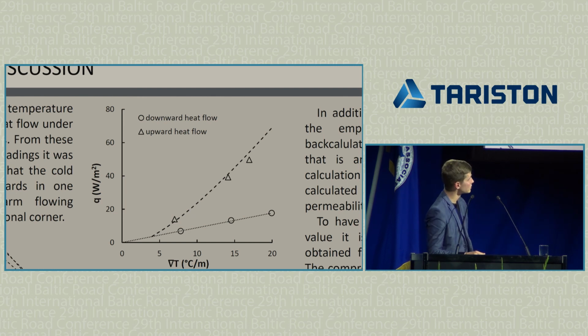After we did this test, we also tested crushed materials. Also this kind of typical sub-base material that they use in Norway, which is without the fines, and you can have convection in those materials too. I know at least in Latvia they use finer gradations, but they also produce materials without the fines. The railways usually use the typical ballast material.